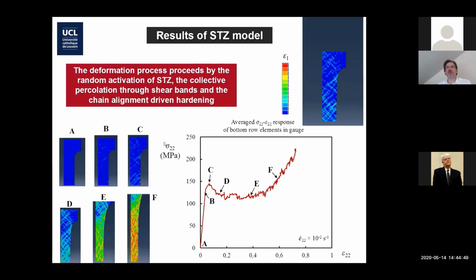These are some more snapshots taken at different deformation steps. This is in tension, just to show you that at B here, we start having the first activations below the peak, and the peak stress is when we start percolating some pattern of shear bands, a collective behavior of some STZ, now creating plasticity which goes to the macro scale. And during the softening, that's when we have this pattern developing into the entire specimen, and the rehardening starts after 40%. Okay.